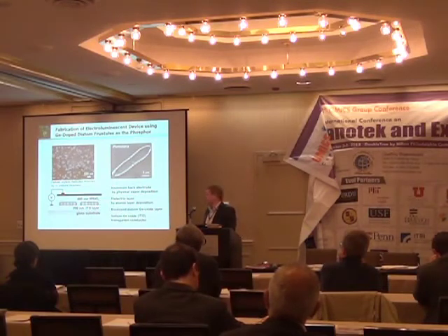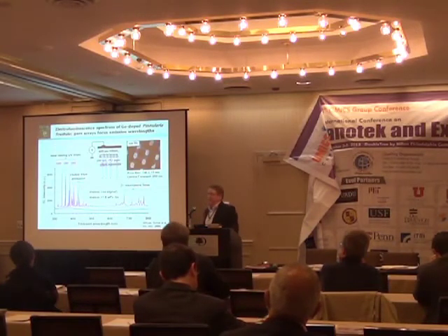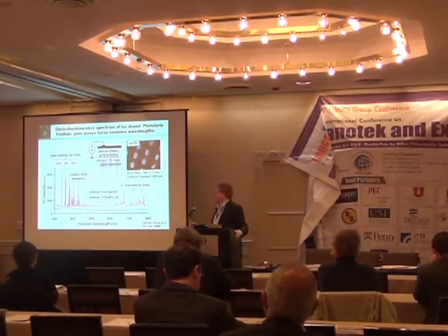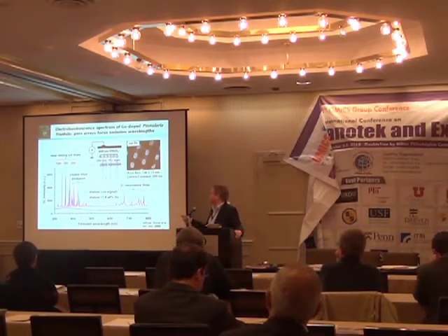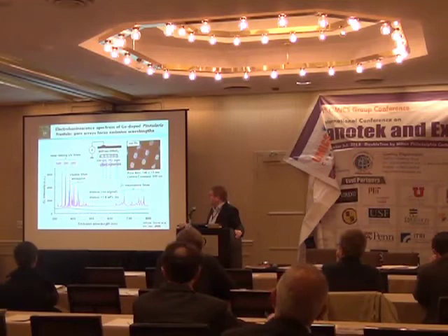So here's an example of the type of emission characteristics you can get from this. If you just use the silica itself, you don't get any signal, but when you have the biologically doped germanium diatoms in here, you get a pretty strong focused emission.